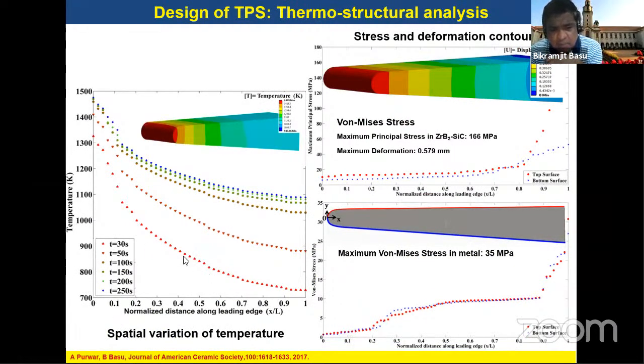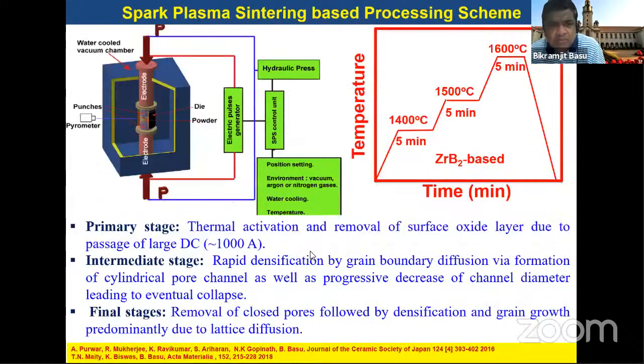If you look at this normalized distance from the leading edge, at the leading edge the temperature at these particular aerothermodynamic conditions is expected to increase to more than 1200, or 1200 to 1400 Kelvin. And this is the maximum principal stress. If you see, maximum principal stresses can go as high as 100 megapascal or so. The maximum principal stress is around 166 megapascal, and maximum deformation is 0.6 millimeter. And if you consider von Mises stresses, it is around 35 MPa that the titanium or underlying metal would experience.